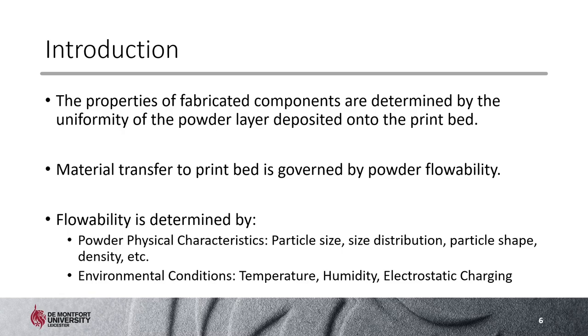The particle transfer from the feed bin to the print bed is directly influenced by the flowability of the powders. There are a number of parameters affecting powder flowability. These can be divided into main categories of physical characteristics and environmental conditions. Physical characteristics include particle size, particle size distribution, shape of the particles, and density of the powder. In terms of environmental conditions, we have temperature, humidity, and electrostatic charging of the particles — all of which can affect how the powder flows.